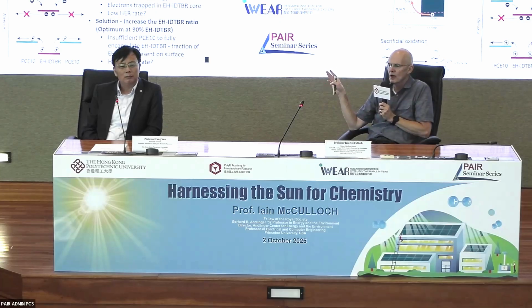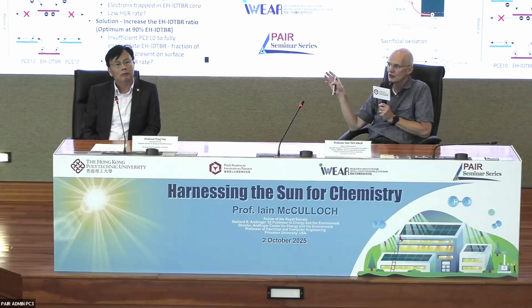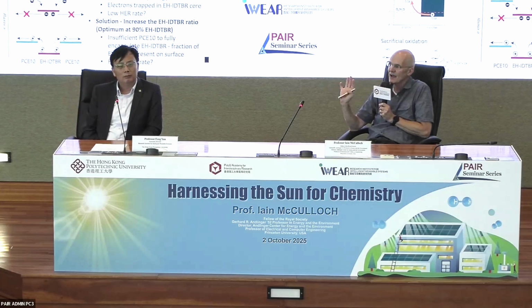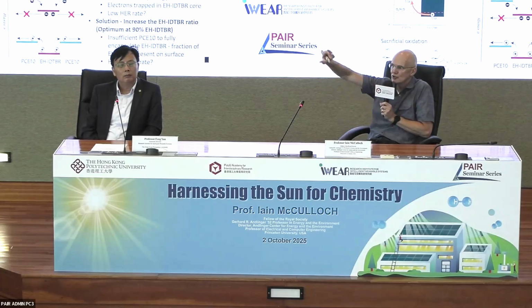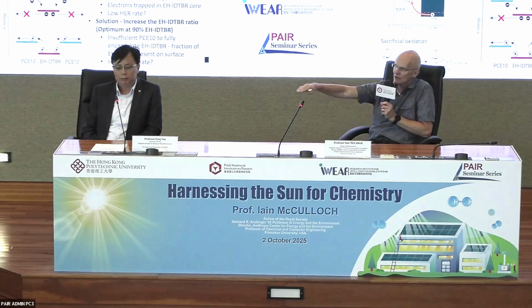But it's very difficult, and the problem is that the literature is not helpful. If you look at every organic photocatalyst in the literature, the typical irradiation intensity is 5 suns. We can't even get to 5 suns in our lab. It's a hazard, right? So that's not reasonable. And the EQEs are so low that you have to monitor the nitrogen along with the oxygen, because if your oxygen is coming in from leaks in your system, the ratio of oxygen to nitrogen won't change. You need the oxygen to be independent of the nitrogen increase.